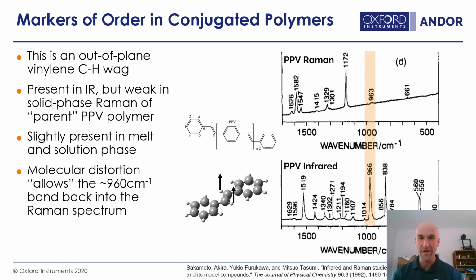So it is slightly present in the melt and solution phase. When we disorder that molecule and we twist it up, bang it around, and decrease its planarity, it will be allowed back into the Raman spectrum. So what we found is that when we pack that polymer film full of bulky acceptor molecules, we decrease the planarity. We squish and squeeze and disrupt the packing to the point where we allow a forbidden mode back into the spectrum by twisting up the planarity of the molecule.